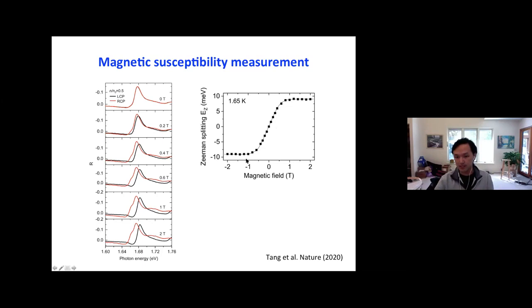And you can extract the slope near 0 Tesla, which is actually the g factor for the Zeeman splitting. And one can show that the g factor here is proportional to the magnetic susceptibility of the local moments. And as I explained, the local moments first get aligned by the small magnetic field and then saturate for magnetic field above 1 Tesla. So this provides us a method to actually measure the magnetic susceptibility, not super quantitatively because we don't really know this proportionality factor, not like SQUID, where we can really perform a quantitative measurement of chi.